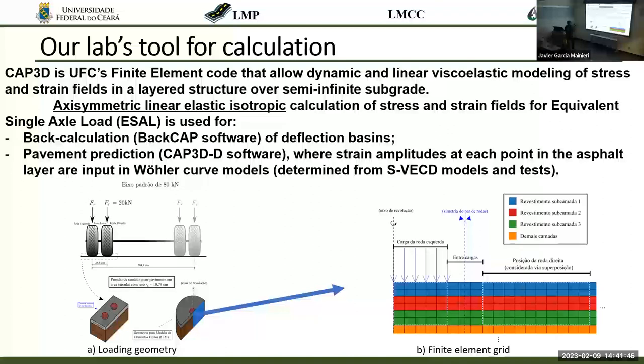We have a software that does many kinds of calculation, transient linear viscoelastic calculations. We can do dynamics, we can do many things, but for pavement design, we decided not to. We decided to simplify it as much as possible. So we have an elastic axisymmetrical calculation, but we have the modulus of the asphalt layer that can change in depth depending on temperature. Let's say here it's very hot and here it is less hot. You can have different modulus inside the asphalt layer. This is something we did not want to simplify because we know it's too important. And so this is what we do, but it's a linear elastic calculation using an elastic modulus equivalent in temperature and frequency to the viscoelastic models.